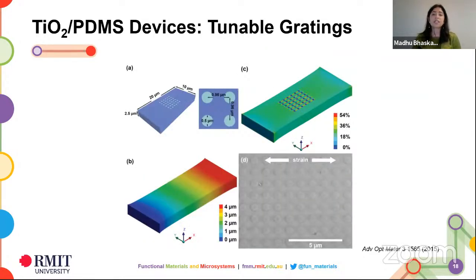And another interesting factor which we found was that we did some finite element modeling with this, and we found that because you have little discs of titanium dioxide sitting in the PDMS, it's the PDMS which basically absorbs all the strain. So the silicone rubber is absorbing all the strain, and the little discs of titanium dioxide are almost mechanically invisible. Because they don't see the strain as much, that's the main reason you're able to strain these up to around 20% and still keep reusing these devices without any issues, which you would not be able to do if you just had a standard layer of titanium dioxide sitting on top as a thin film.